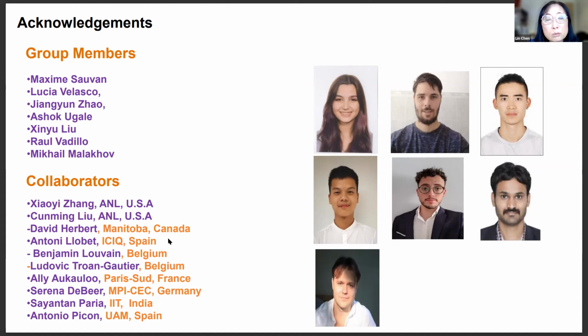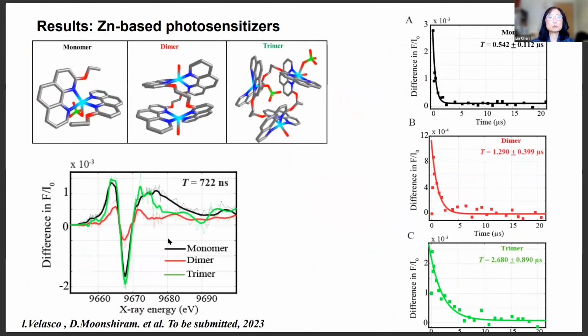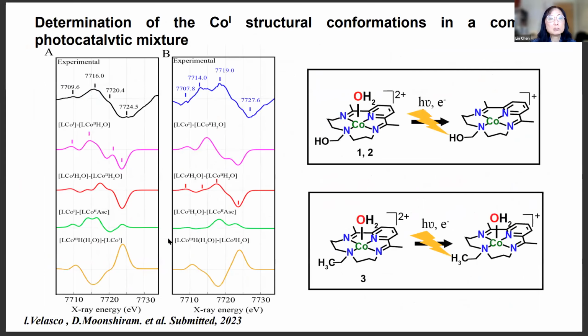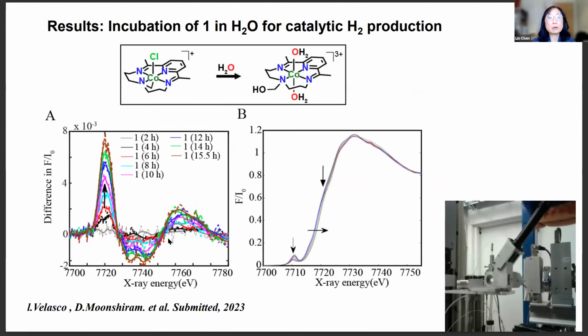Yes, thank you so much for this wonderful talk. I have a question regarding this cobalt catalyst. I was intrigued by your observation of this continuous shift during the time of, what, 10 hours, 15 hours? That's a really long time. Did you observe this continuous changing or did it actually stop? Because we studied a similar cobalt catalyst complex and we observed the continuous change, but we thought that the sample was degraded. Even when we put it in the dark, in the drawer, with no X-ray, no laser, it still changed overnight. So did someone do NMR or some characterization to confirm that is the product?